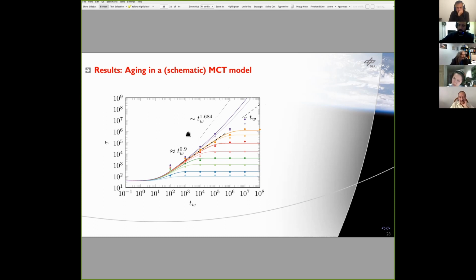So, reminder, the prediction is that for quenches right to the glass transition, we should observe normal aging, tau proportional to TW. And for all the quenches to states below the glass transition, we should observe eventually a constant, because the system equilibrates, and that's obviously observed and in agreement with the theory.